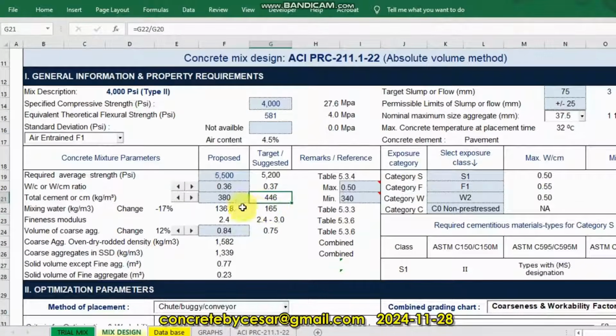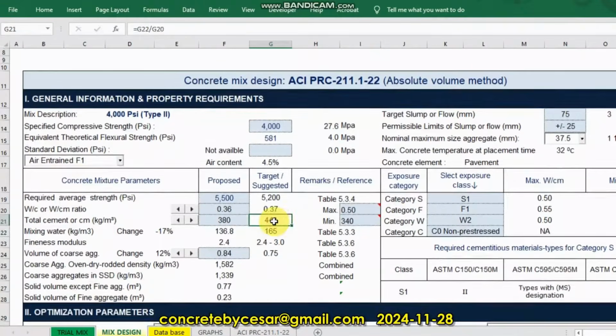Before moving forward, I just want to point out that originally from our guidebook, the formula for cement content is mixing water, wherein you have to refer to table 5.3.3, mixing water in kilogram per cubic meter, divided by the water cement ratio, which will equate to 446 cement content. I just want to explain that I'm still respecting the guidebook, so I decided to mention all this target or suggested value based on the guidebook. However, this will be our proposed value since we are designing the concrete in a much more practical way, especially when you are in the ready-mix concrete field of industry.